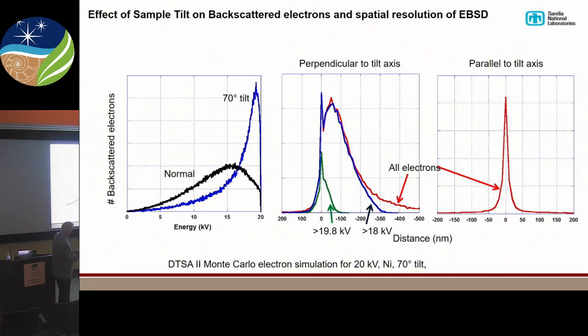Now, the ones that lose more energy than that, all these out here, if we look at higher losses, like 2 kV, they contribute to the background of the pattern, the overall background level, as we call it. They do diffract, but they don't diffract into these nice bands that we see. So that's why we can get resolution much better than you're used to seeing in normal backscatter images.